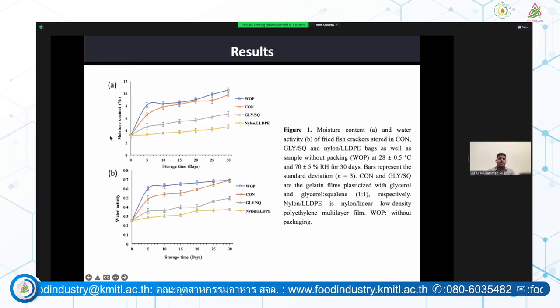During the storage studies, we have determined the various parameters of the crackers. Here we can see the moisture content of crackers without packing, with the control, with glycerol, this is glycerol with squalene, and this is commercial packaging. The moisture content of crackers was least in the commercial packaging, and next was the squalene incorporated packaging. Similar results were observed for the water activity. This indicated that the water vapor permeability was lower, and the fish crackers could remain intact for several days.